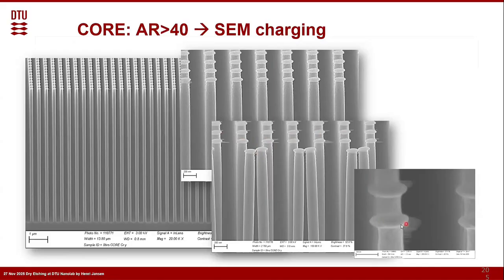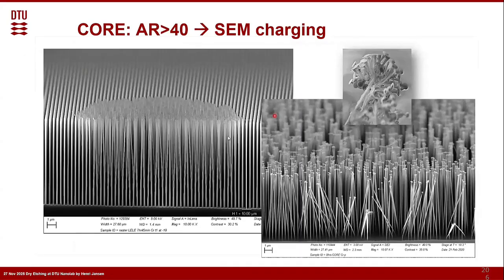This is why you see this kind of vibration. It's not because the structure itself would vibrate, but because of the electron charge. The electrons are charging it, and the pillars start to move around with respect to each other. It can go so far that they really start to cluster. So here we looked with the SEM for a while, and they all stick together. You can see that the rest is still fine.